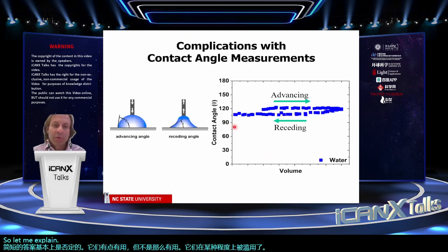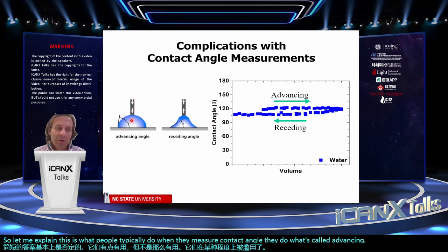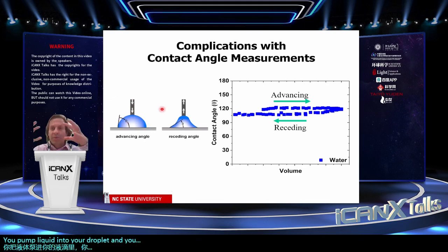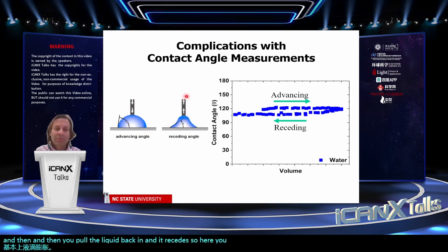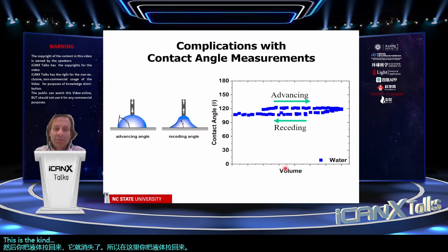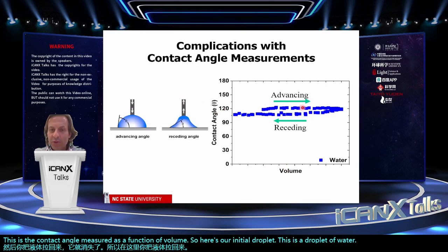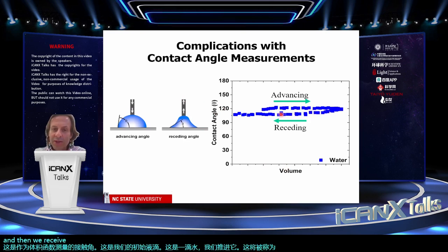This is what people typically do when they measure contact angle. They do what's called advancing angle, which is where you pump liquid into your droplet and the droplet expands. And then you pull the liquid back in and it recedes. This is the contact angle measured as a function of volume. So here's our initial droplet. This is a droplet of water, and we advance it. This would be called the advancing contact angle. And then we recede it. This would be called the receding contact angle.